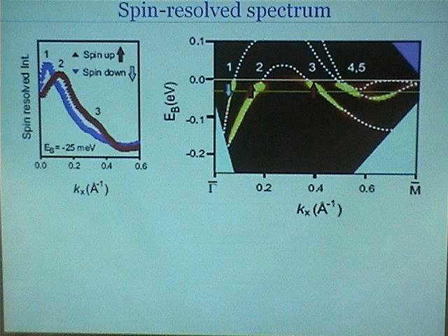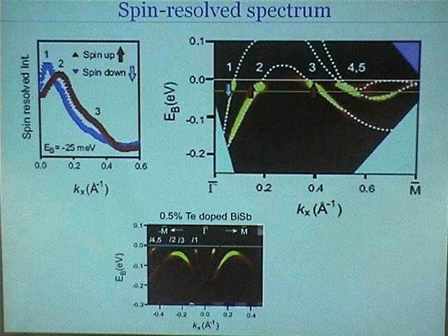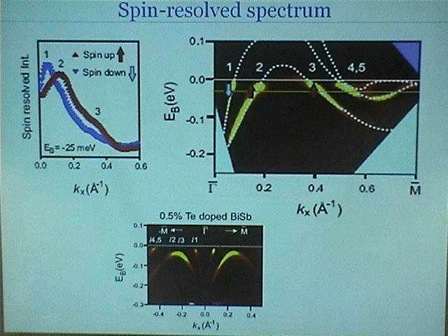They don't carry a topological quantum number. And there is a simple way to check that the spin assignment is correct. All you do is dope the surface. If you put electrons on the surface, the Fermi level rises, and you do see that they connect up. So I know right away, out of the 5 surface states, I got rid of 2.